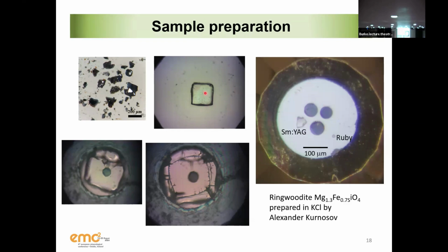And you can see this. This is a nice crystal of KCl, I think. This crystal cannot just be picked up from the synthesis. Usually, if you have an anisotropic material, it has to be oriented, double-side polished, down to possibly less than 10 microns. That's why Raphael is absolutely indispensable. And cut with the FIB such that the dimensions are exactly the dimensions of your laser.